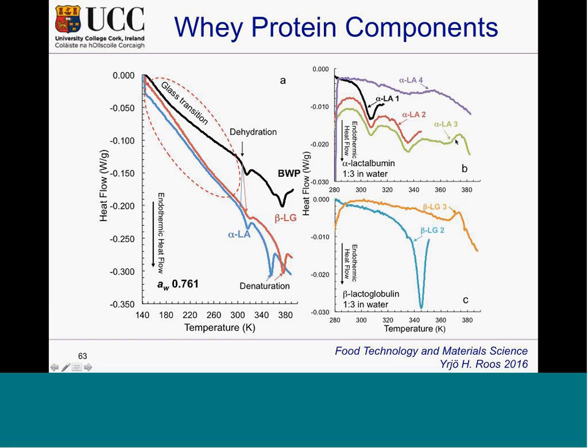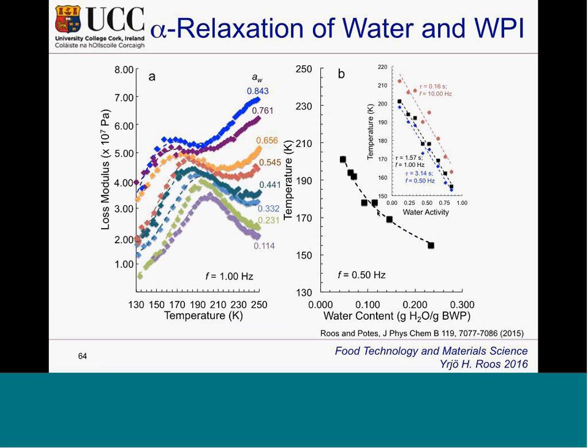The low temperature protein transition could actually be a transition, or actually an alpha relaxation, of hydration water on the surface of the protein. That is something that confuses many studies, because you may claim that there's a glass transition of the protein, but it's not. It's a glass transition of water that is separated from the protein, and we had the establishment of that. But that allowed us, with the fraction of water sorption, for the first time to complete a diagram for a mix of protein and sugar.